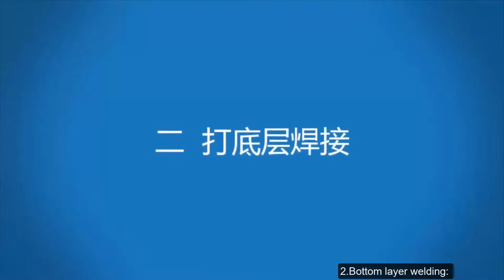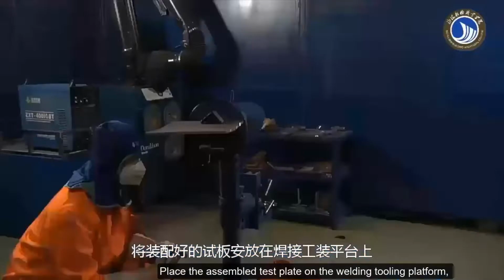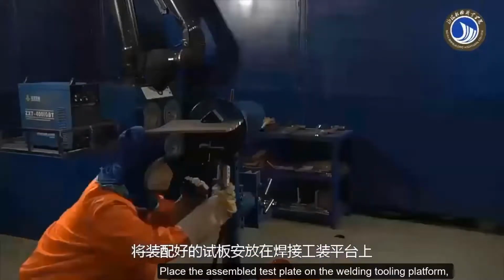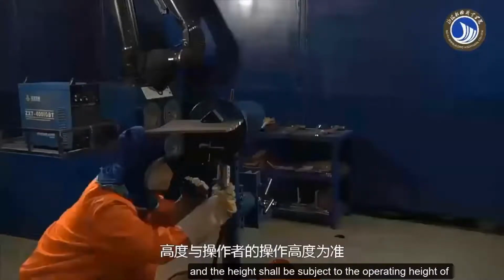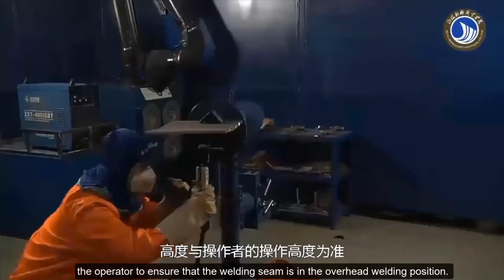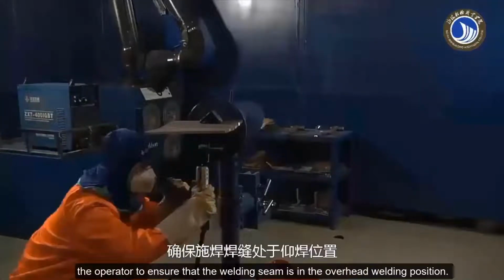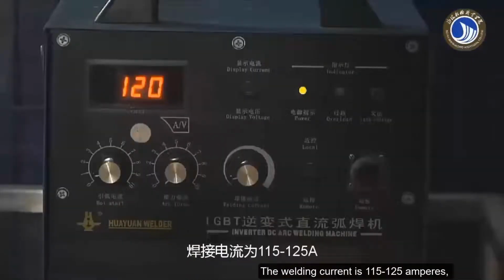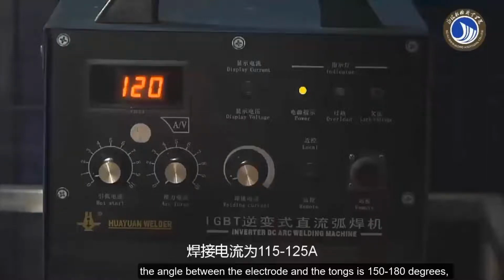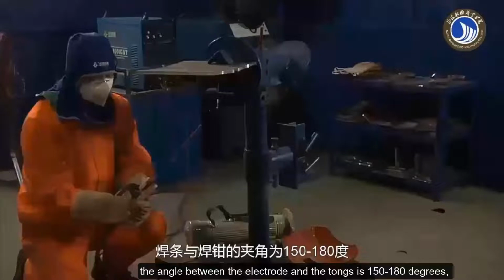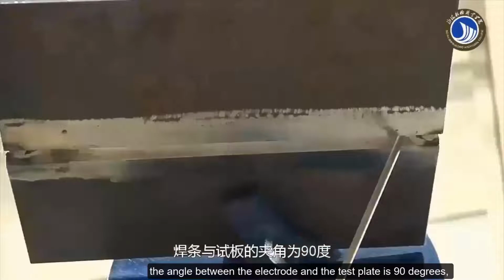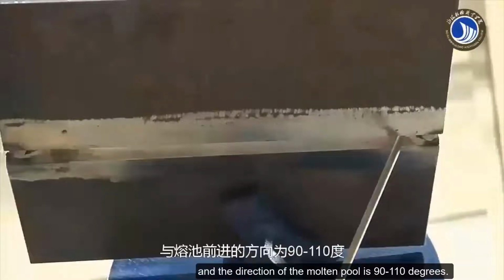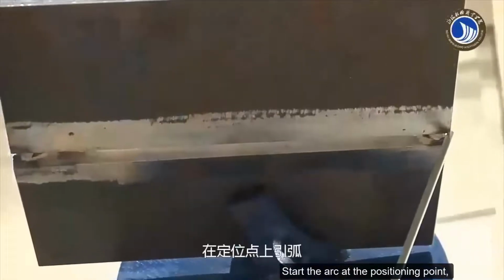2. Bottom layer welding. Place the assembled test plate on the welding tooling platform, and the height shall be subject to the operating height of the operator to ensure that the welding seam is in the overhead welding position. The welding current is 115 to 125 amperes. The angle between the electrode and the tongs is 150 to 180 degrees. The angle between the electrode and the test plate is 90 degrees, and the direction of the molten pool is 90 to 110 degrees. Start the arc at the positioning point.